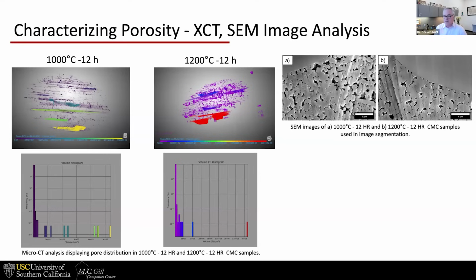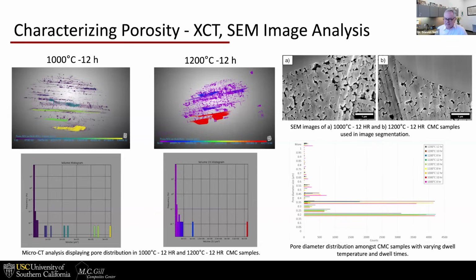These images here on the right show what porosity looks like. This is the type of porosity that we want to achieve by design. This is not a problem. This is actually what we call good porosity. And this is some statistical distribution of the pore diameters. These pores here tend to be relatively equiaxed.